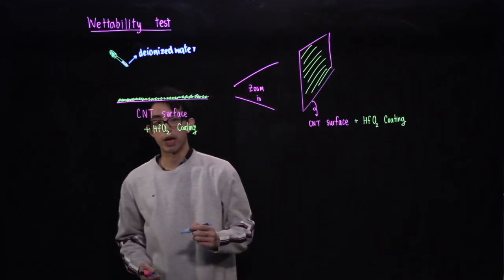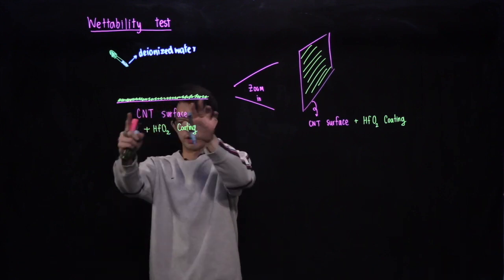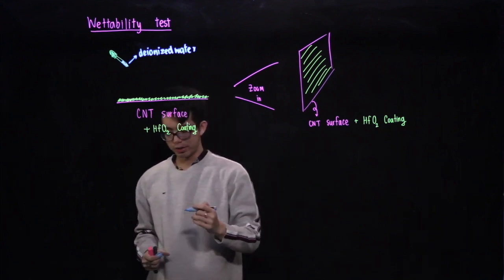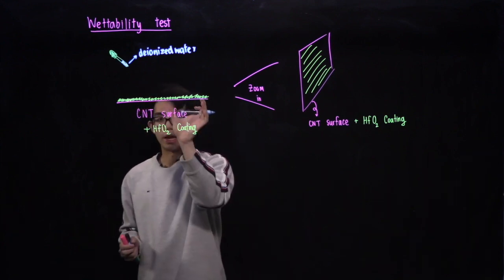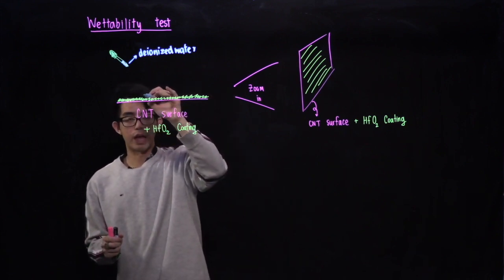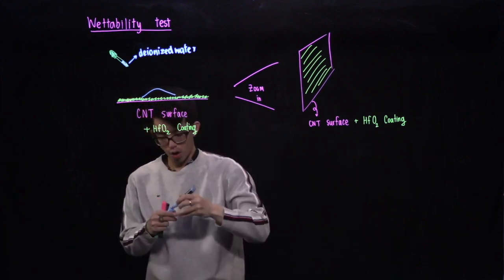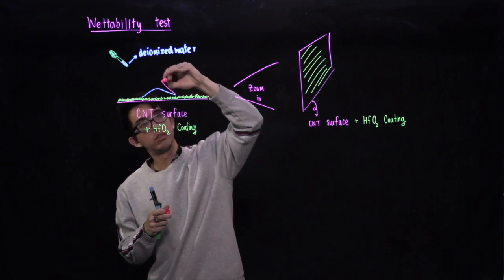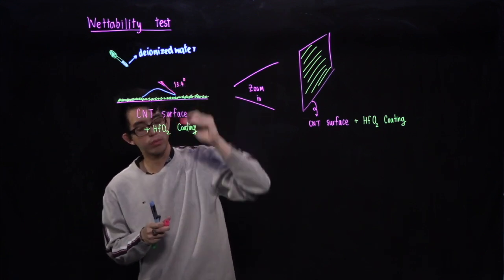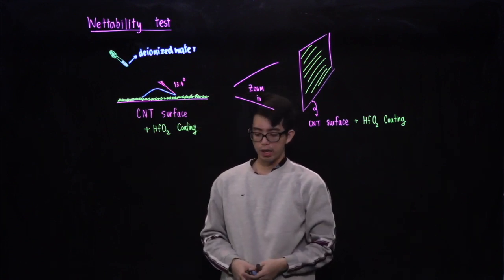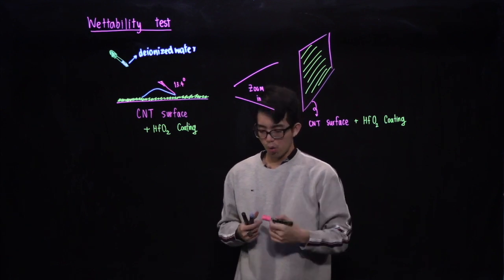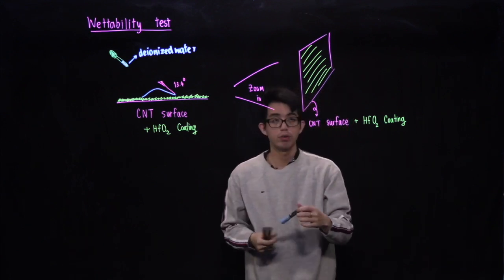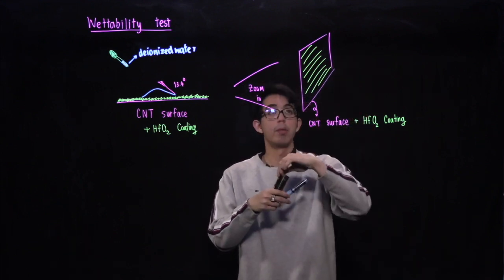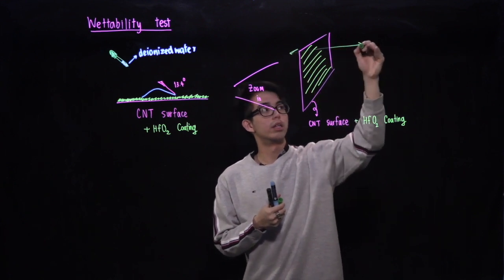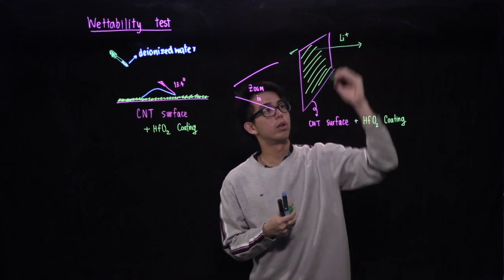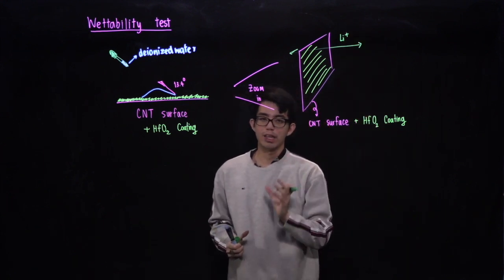Okay, in the case of hafnium oxide coating, the hafnium oxide layer here would greatly improve the surface interaction between the deionized water and the surface. So the contact angle now will decrease to only 13.4 degrees. According to this excellent wettability property, it would greatly increase the quantity of active sites available on the surface, and it also allows lithium to permeate through this separator, carbon nanotube. And it also does exactly what we want it to do.